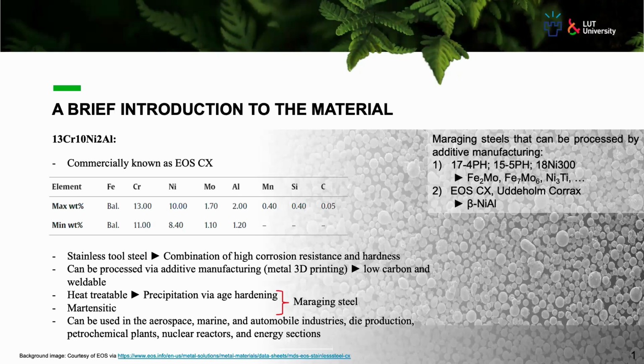The high hardness of these steels after heat treatment heavily relies on complex compounds comprised of, for example, iron-molybdenum or nickel-titanium particles. However, the problem was that these kinds of particles have limited stability at high temperature. So to resolve these issues, the next generation was developed by companies like EOS or Uddeholm, and they used beta nickel aluminum particles to make these materials precipitation hardening.